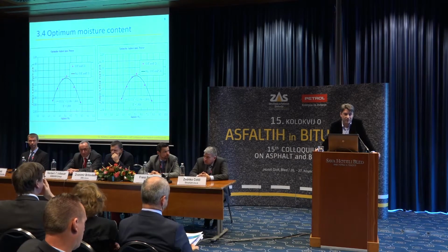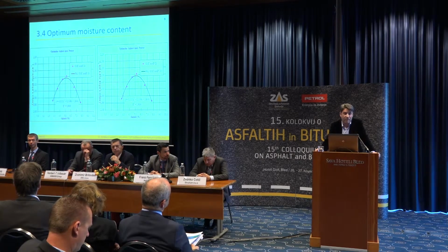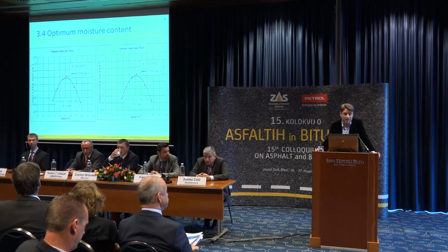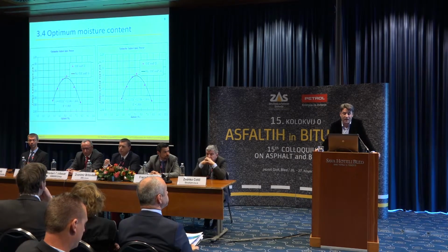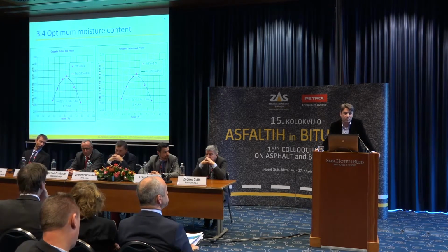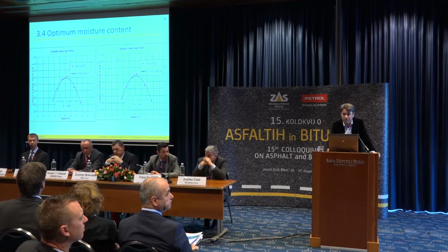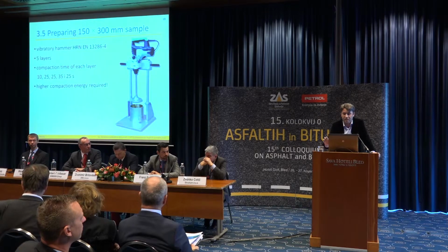And the reason for that is because you have a sample that you compact in a split mold, and you lose fine mortar material that goes through this split mold, and it seems like you have to add more and more water, and it doesn't stop. So this procedure of finding optimum moisture content using a vibratory hammer doesn't work, even though some people try to explain that it does, but it didn't work with us.